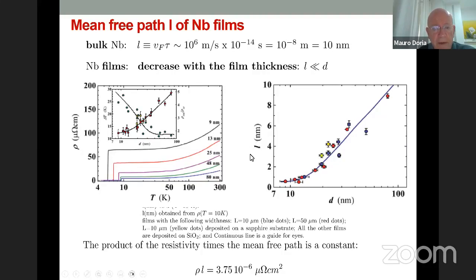And how do you obtain the mean free path? Is it the same because it's niobium? No, it's not the same. The mean free path varies according to the thickness of the film. And how is it computed? This is an interesting observation. You can use Drude's model. You take the bulk, and I will describe this some more, the resistivity times the mean free path is a constant. It's a number that depends only on the density of electrons and the mass of the carriers. So using this formula, you take this resistivity here, which is the normal state resistivity, and you compute the mean free path here using this value.